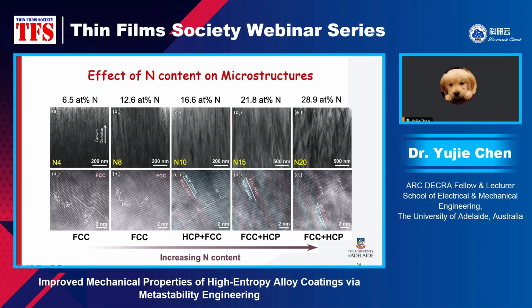So the highest nitrogen content is 28.9 atomic percent. But it's a high resolution STEM image. It doesn't show any nanoparticles of nitride. It looks like we have successfully dissolved a massive amount of nitrogen into the FCC and HCP lattice.